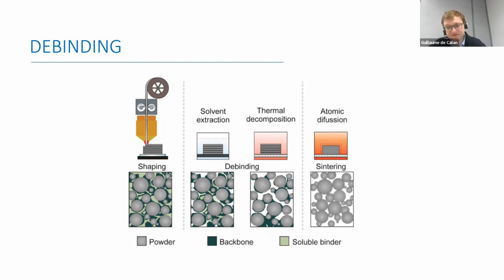This explains a bit what's happening in the process. Most of our filaments use a two-step debinding process. That means chemical debinding and then thermal debinding. Chemical debinding is done with acetone, and thermal debinding is done in the furnace just before sintering. What happens actually is that in our filament, you have several binders. You have a backbone and a soluble binder. The soluble binder will be removed during the first step. That helps a lot the following process, because the first thing is it removes half of the binder, and it also creates a network of porosity that will help you remove the rest of the binder, which is actually going to be burnt out, and so the gases of this burnout can come out of the part more easily.